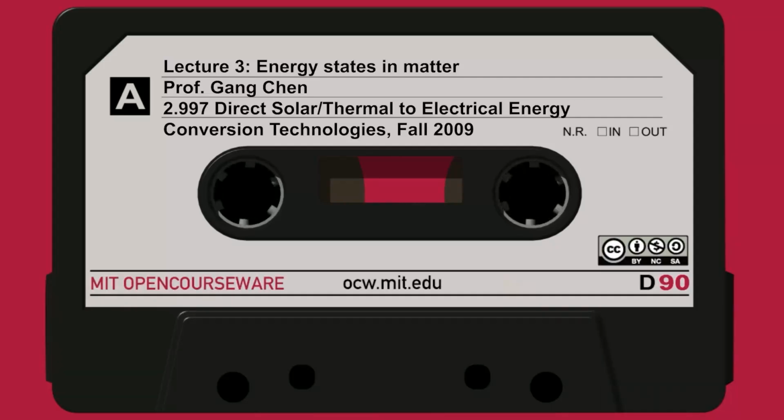It's much harder stretching at the higher frequency, stiffer. So in this case, we have two types, as we have two atoms. One is the acoustic branch. That's the bottom part. That's this picture here, roughly. The other is the out-of-phase one. That's the optical branch. Okay. So that's the atomic vibration in one dimension.